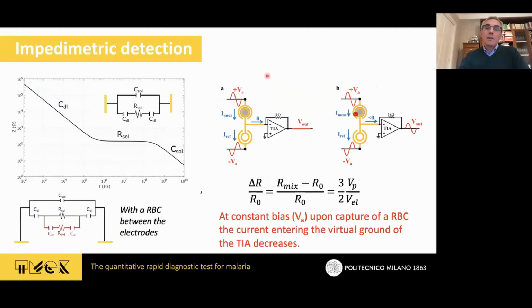So essentially what happens is depicted here. We have the measurement electrode here, we have the reference electrode, and we apply two signals which are out of phase. You see plus VA and minus VA here, in order to have what? In case of perfect balance between these two resistors, the measurement and the reference, we have zero current flowing into the virtual ground of this transimpedance amplifier, no signal. But when a particle is captured here, there will be what? An increase in the resistance here. If the resistance increases because you have an insulating particle, there will be a net current that will enter this virtual ground and some output signal that will be generated.